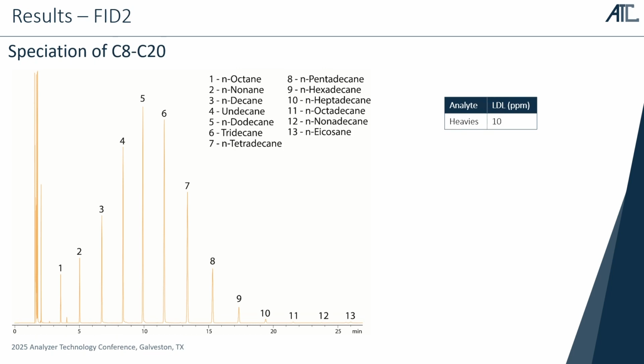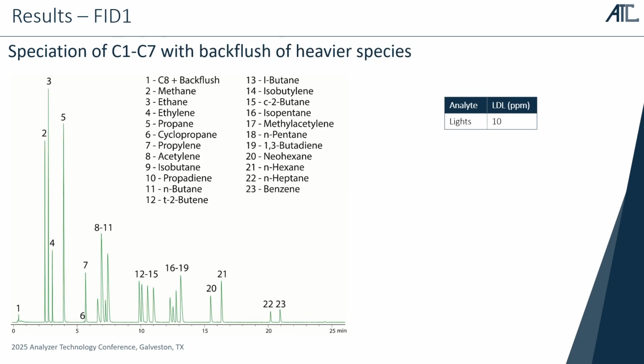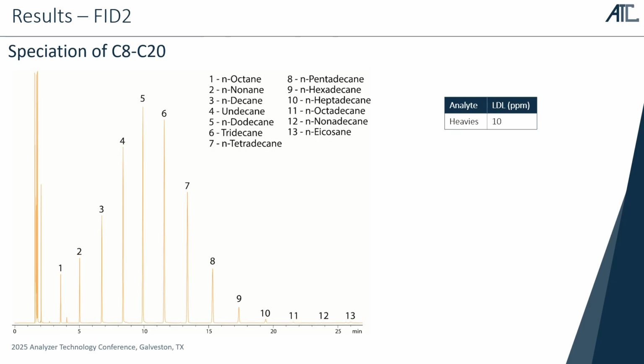As you can see, because we started at a higher temperature on this detector, the benzene and C7 weren't coming off the column till about 20 minutes. Since we have a separate microconvection oven at a hotter temperature, we're able to elute the C20 by around 25 minutes. So with these 3 chromatograms combined, we're getting that whole list of analytes out within about a 30-minute time period, a little bit less than that.